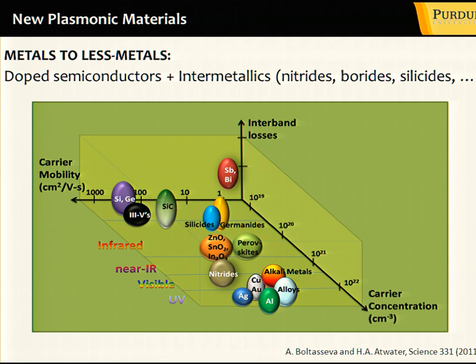Yet another problem, the loss is also proportional to the plasma frequency squared, and having that large plasma frequency just makes losses even larger than we would like them to be. So in a sense, metals are too metallic for us. We would like to have a density of charge carriers, in some cases at least, smaller. Or ideally, we would like to control it. We would like to be able to switch the density of charge carriers to bring it into the range where we want, to make it 1 eV, 2 eV, 0.1 eV, whatever.